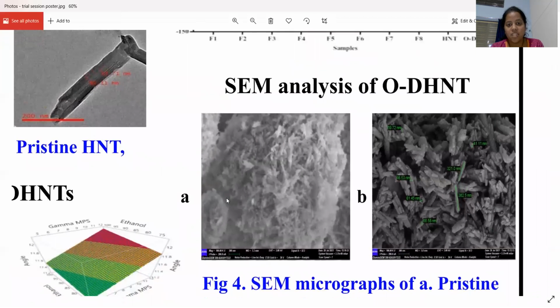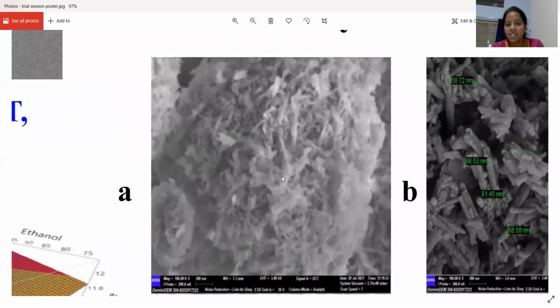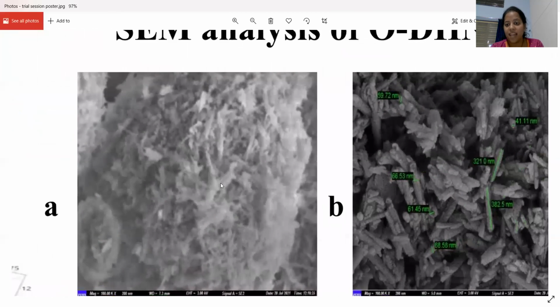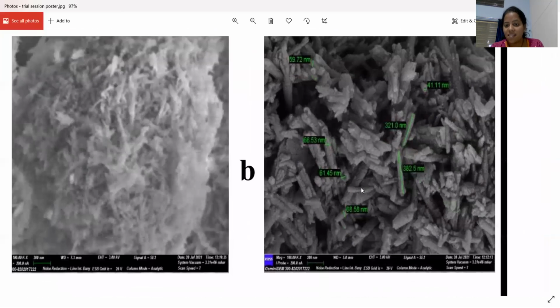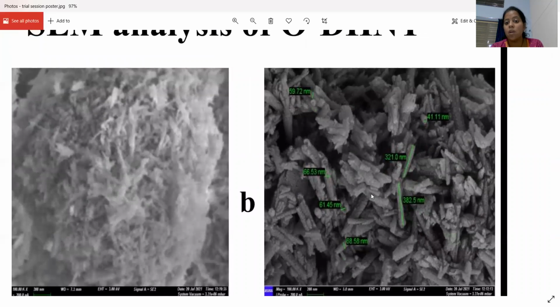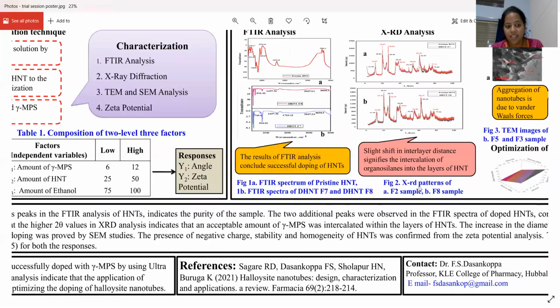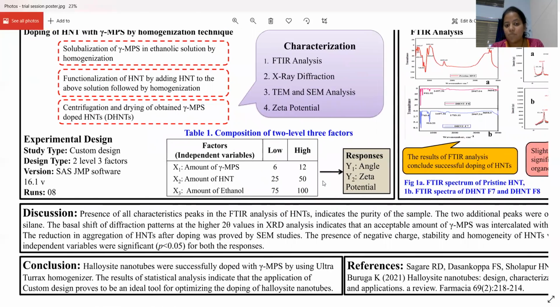less than 0.05. These optimized doped HNTs were characterized by SEM analysis, wherein we could observe the pristine HNT at 100x, the nanotubes were small with an uneven morphology appearing as a cotton cloud of nanotubes. But upon doping at the same magnification, the intensity of the aggregation was drastically reduced and the nanotubes were clearly observable with proper dimensions. Thus, we can conclude that halloysite nanotubes were successfully doped with gamma-MPS using Ultraturrax homogenizer, and